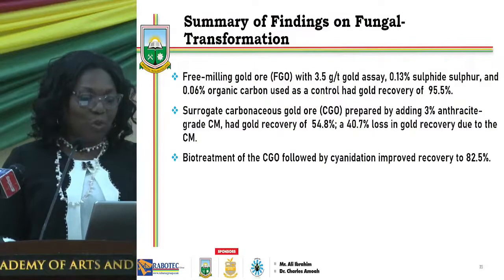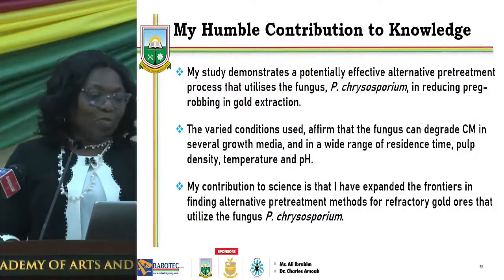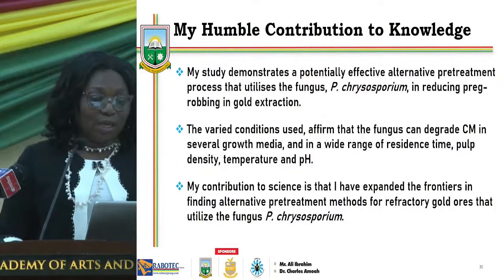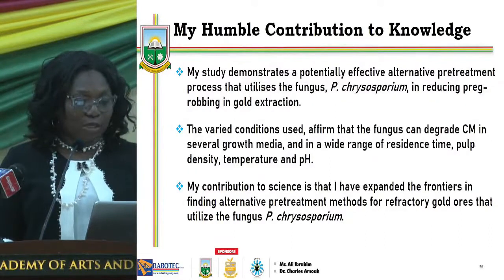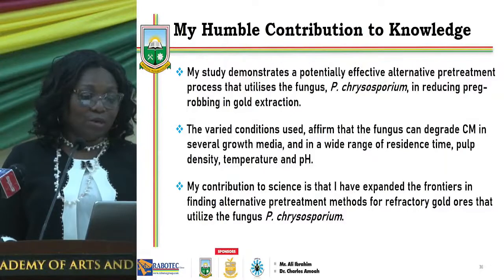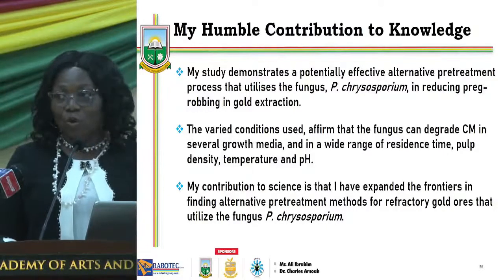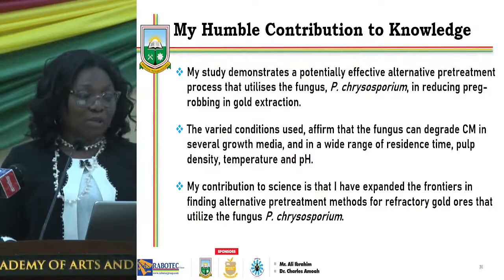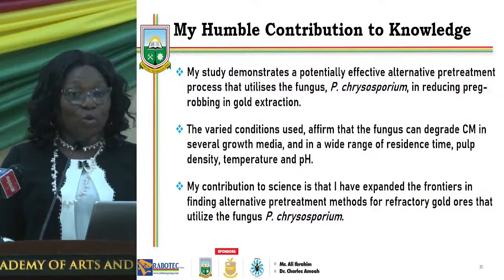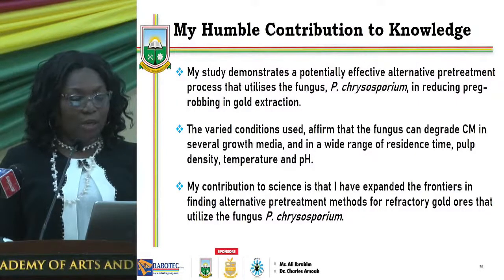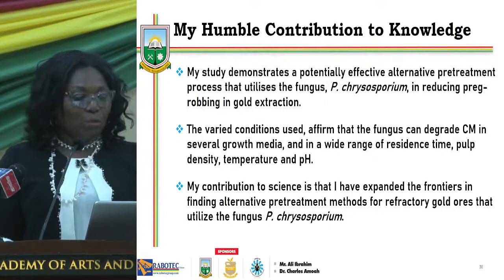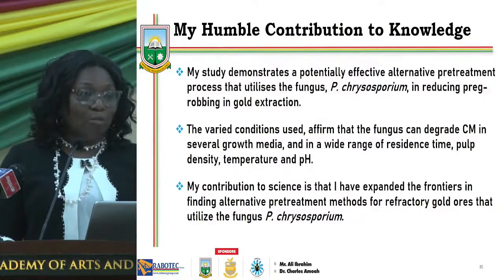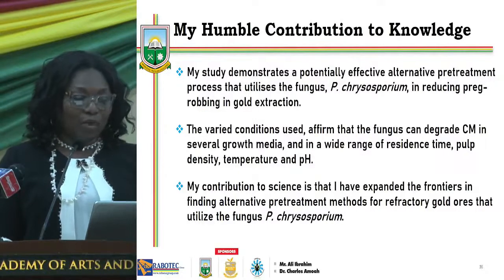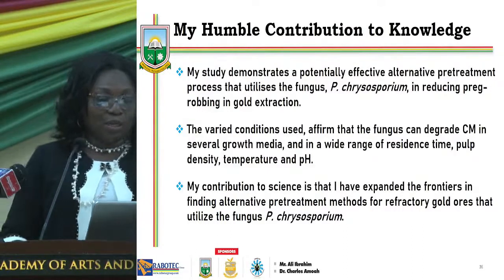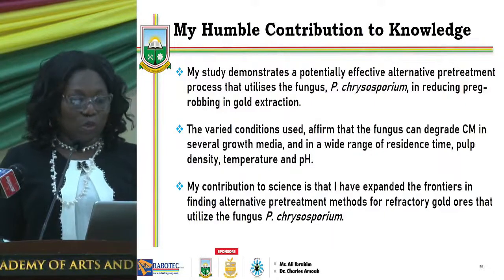Ladies and gentlemen, my humble contribution to knowledge. My study demonstrates a potentially effective alternative pretreatment process that utilizes the fungus Phanerochaete chrysosporium in reducing preg-robbing in gold extraction. The varied conditions used affirm that the fungus can degrade carbonaceous matter in several growth media and in a wide range of residence time, pulp density, temperature, and pH. My contribution to science is that I have expanded the frontiers in finding alternative pretreatment methods for refractory gold ores that utilize the fungus Phanerochaete chrysosporium.